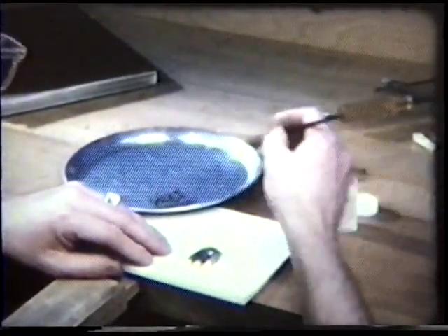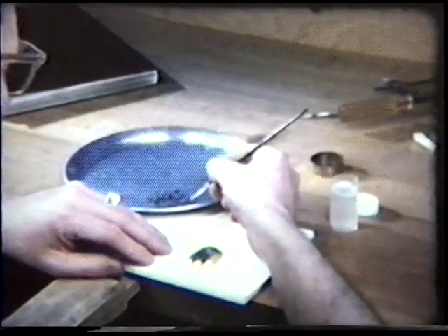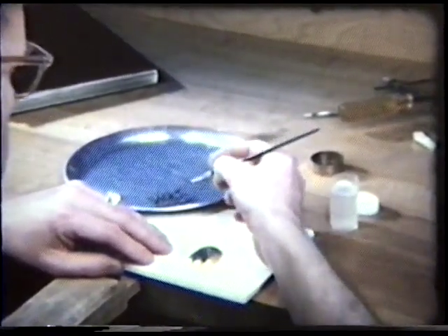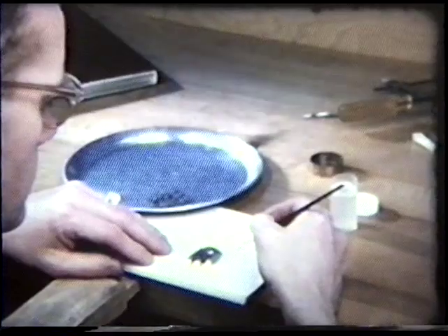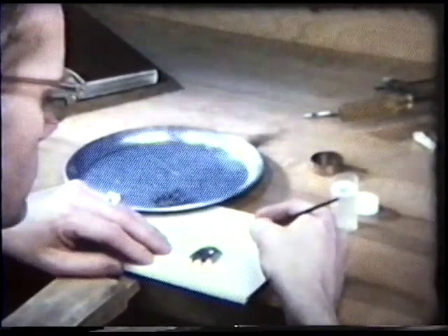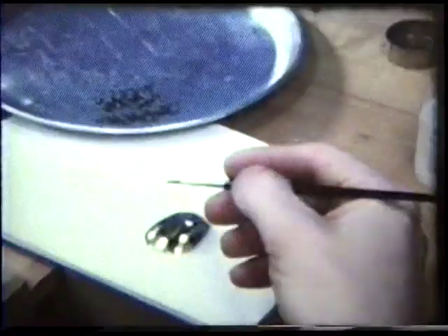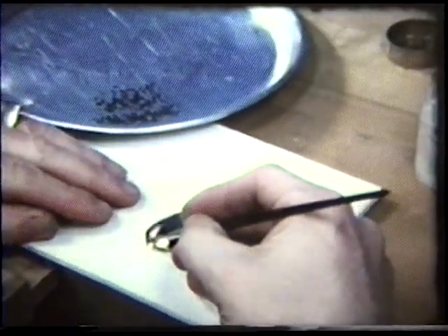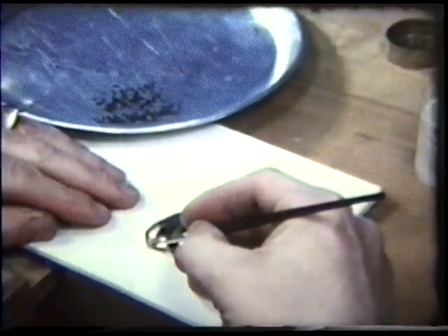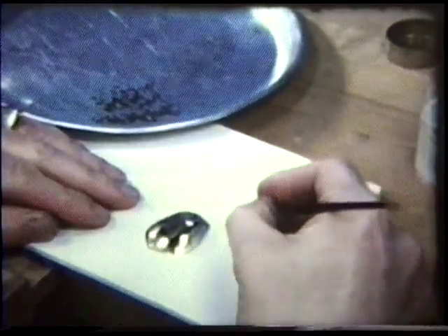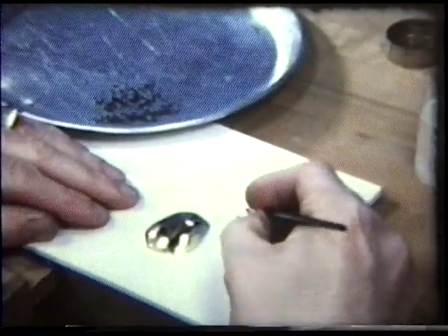The back is now ready for the application of small rectangles of gold, which eventually will form the walls or cloisons bordering the areas of enamel. These rectangles are black due to copper oxide, which has been developed on the surface of the gold by heating them in a kiln at about 1300 degrees for a period of time.